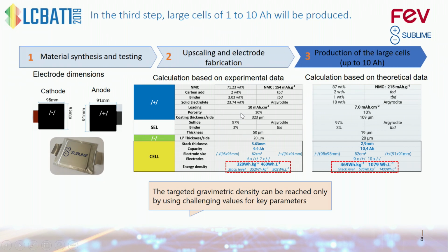So regarding the upscaling for multi-layer pouch cells, and to reach the targets, based on the experimental results that we have at the moment, we are using, let's say, 70% cathode active material in the cathode. We can make electrodes with extremely high mass loading, but the thickness of the solid electrolyte is a bit high, 50 micrometers, and by doing a theoretical calculation, this gives us an energy density of 320 watt-hour per kilogram or 460 watt-hour per liter.